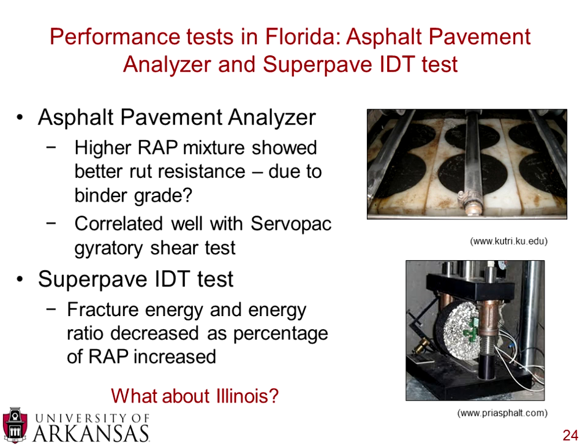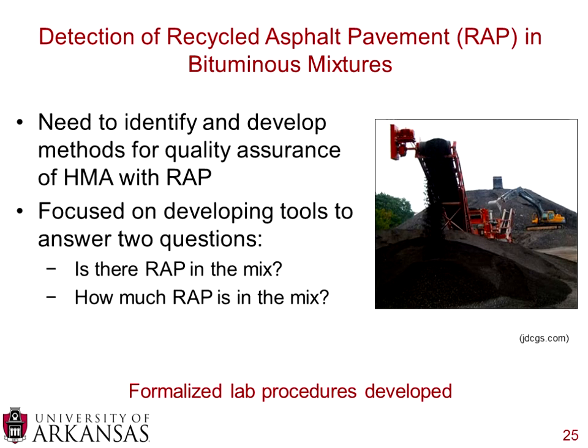So another area that people are looking into is using your gyratory compactors in order to quantify the compactability of your mixture. So you can measure how much shear needs to be applied when you're compacting a sample, and that can get an indication of the compactability or the workability of the mixture. And they found that those measurements from that gyratory shear test correlated well with the asphalt pavement analyzer. For the SuperPave IDT test, this was looking at fracture energy and your energy ratio. They found that both of these decreased as the percentage of RAP increased. So much like the NCHRP 752 report, as you increase the amount of RAP, your ability to maintain cracking resistance decreases.